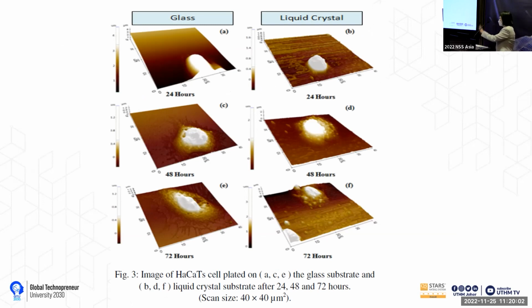That's very common for cell biologists, nothing interesting. But if you put it on the liquid crystal, the cell remains rounded on the substrate because of the low stiffness of the liquid crystal compared to the glass substrate. Right, so that's interesting. I mean, the application of AFM in imaging this. Right? If you put it in the FESEM, then because of the liquid crystal, it will actually disturb the electron flow, right? So FESEM may not give you all the solution, especially when we are dealing with some, what do you call that term? Amorphous material, sorry. Amorphous material, yeah.